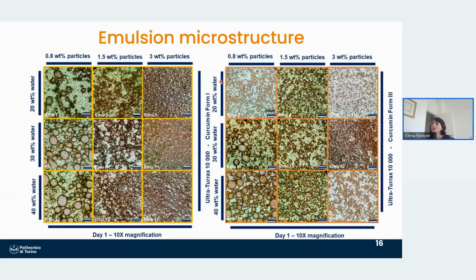Now, by playing with the concentration of water and the percentage of particles, we can get different size distributions of the water droplets, so we can get different textures in the food. More particles and more water also determines smaller droplets. And as you can see, in general, with form 3, which is a slightly better stabilizer, with the same conditions, we get slightly smaller droplets, smaller and a little bit more stable.